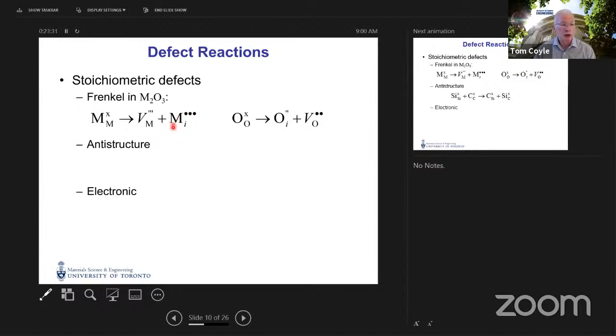One place it could go is an interstitial position where the effective charge would be +3 because normally there would be no charge there. Is it balanced? Well, we have one cation on the left, one cation on the right, so mass is balanced. We have one cation site on the left, one cation site on the right. Sites are balanced. And we have a relative -3 and a relative +3 charge, so charge is balanced. Similarly, for a Frenkel defect on the oxygen sublattice, oxygen from an oxygen site moves to an interstitial site. And again, mass, charge, and site are balanced.